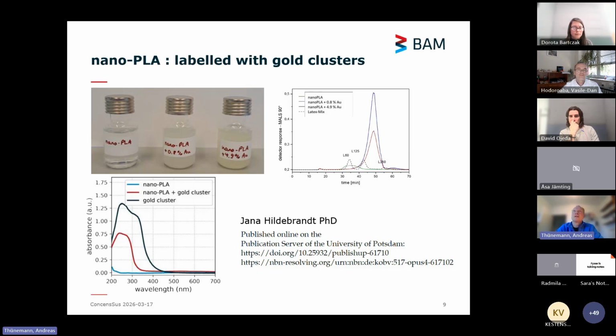Size exclusion chromatography proves that the gold particles are really incorporated in the nanoplastic particles, and this was also supported by UV spectroscopy.